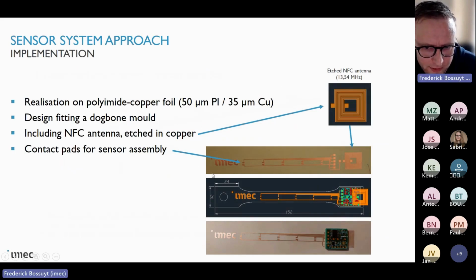So these are the current realizations. We're realizing these foils based on polyimide copper foils. Typically, the polyimide is about 50 micron and the copper 35 micron. We started with designs fitting in a dog bone shape to do characterization before going now to the actual crash box. So we have the NFC antenna directly etched in the copper, and then we have also the contact pads for the assembly of the strain gauge sensors.